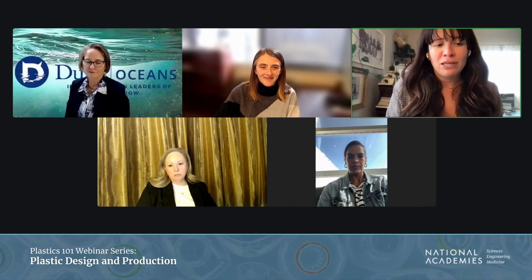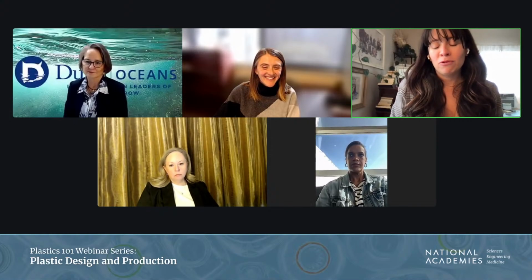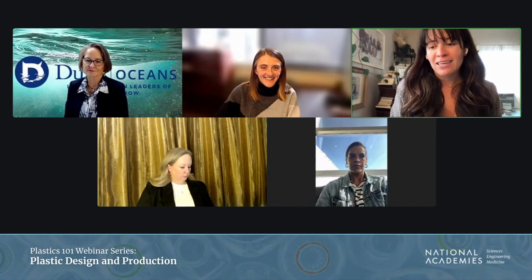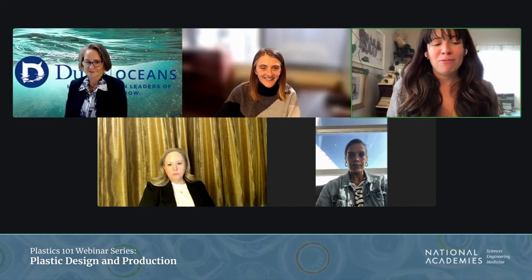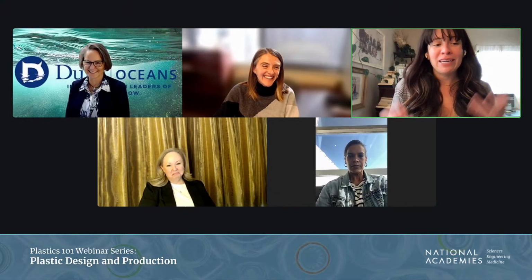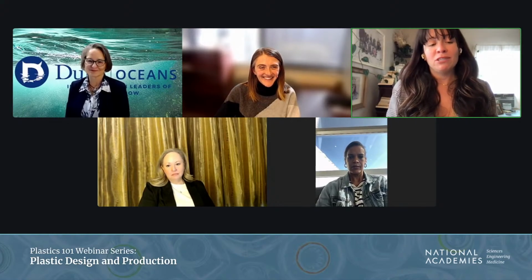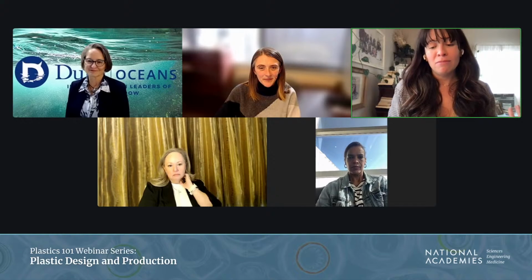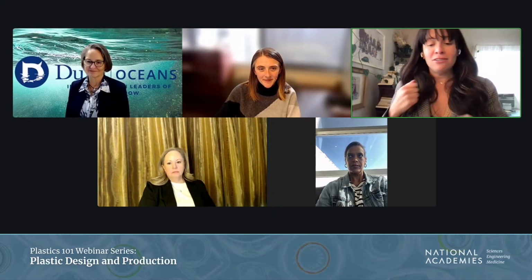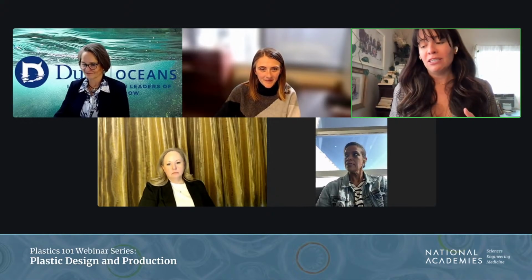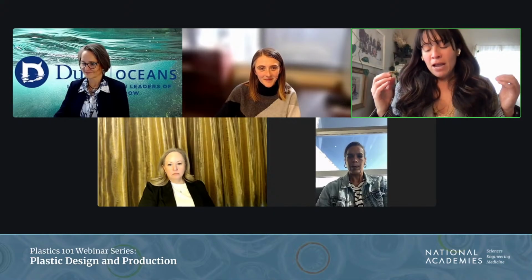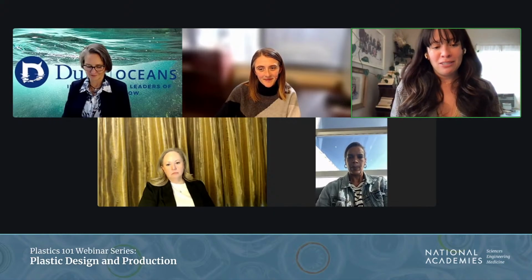Yeah, can I just add one more thing there from Michelle? I could not agree more that there are materials that, if I say out loud, I'm going to probably get some pushback from people eventually, but polystyrene, PVC, materials that continue to be used because they're cheap and we can mold them because we can add plasticizers and things that make them highly amenable to different processing tools, but are incredibly problematic in these recycling streams.